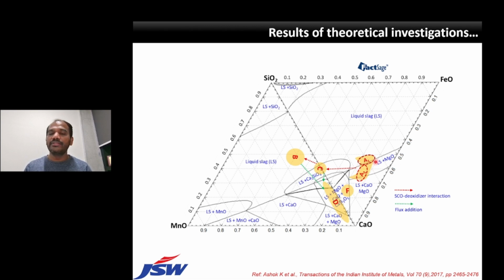You can see this is the BOF slag composition regime, A1 and A2. A1 is completely liquid and A2 is liquid slag plus some saturated MgO. And when the deoxidizers are added, the BOF slag moves to this regime of liquid slag plus dicalcium silicate, or regime B, where the liquid slag is there. And upon the flux additions, these B and C regime compositions move to a final composition of D and F. This is how the slag path travels in case of the tapping process.